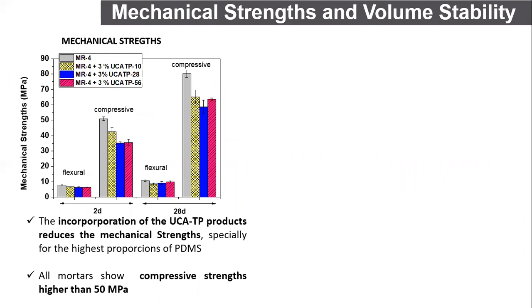Well, so in this slide, I show you the results corresponding to the mechanical strengths. In general terms, the incorporation of InnovaConcrete products reduces the mechanical strengths, and this reduction is higher with the increasing proportion of polydimethylsiloxane in the product. However, we can see after 28 days that all the mortars show mechanical strength values over 50 megapascals, which is more than enough for this kind of substrates.